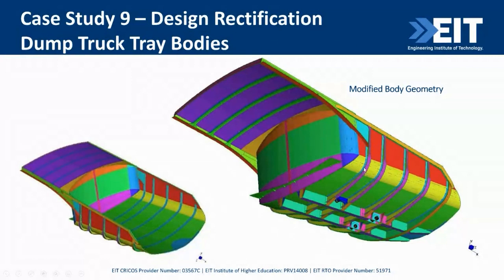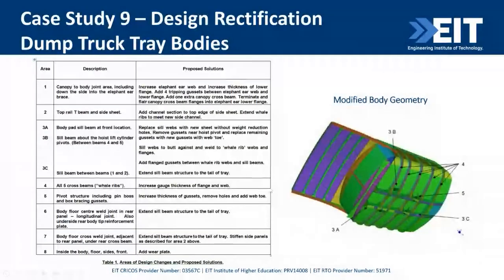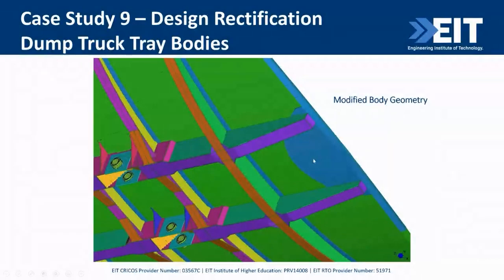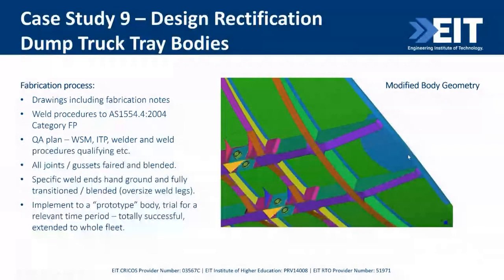And you can see there the modified body, you've got your tail fully supported into your longitudinals. You've got your laterals all the way up to the top of the tray. You've got more ribs on the canopy. You've got better elephant ear detailing with a flange. And the whole lot is structural continuity. There's no gaps or no hot spots or load paths which stop. You've got structural continuity and fairing flanges and web gussets, etc. And that worked very well to be rectified on a prototype, one of the prototypes, and then it went through the whole fleet. So that was a good result. And at the same time, the shovel operators, we had a team meeting with them, and the roads were improved, and it was a good result.